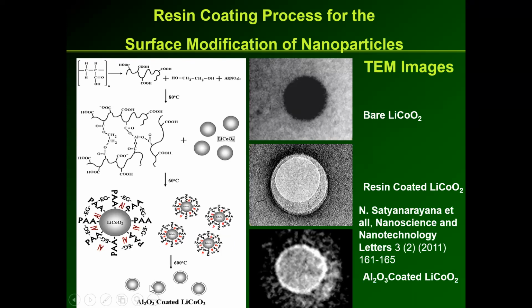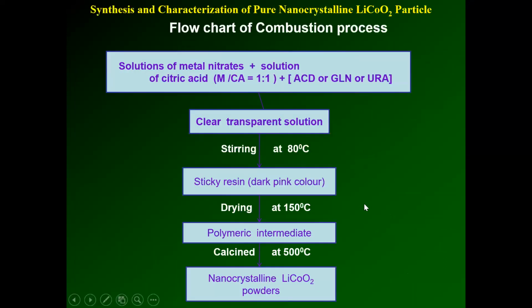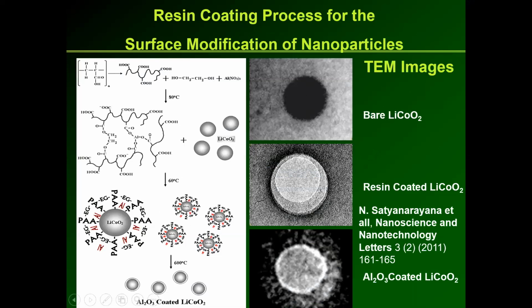Again, this schematic diagram is confirmed directly from the TEM. So you can see that this is the TEM of lithium cobalt oxide nanoparticles. To this, we have coated the resin. This is the resin. Then when it is fired, polyacrylic acid and ethylene glycol are gone. So aluminum and oxygen form aluminum oxide over the lithium cobalt oxide nanoparticles. So this is a nano coating. We have developed this resin coating technique for surface modification of any nanoparticles. So this can be extended to a variety of compounds. This is what I showed as the output with the schematic.